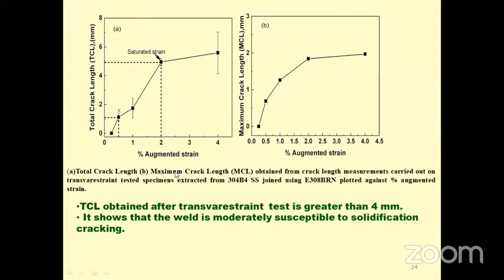So when we tested this material, we also saw that because the total crack length is above 4 mm, it is moderately susceptible to cracking. Whenever we want to use this electrode for an application where the restraint is lower, that is, the geometrical restraint or the thickness of the base metal to be welded is smaller, we can go for this electrode because the restraint expected in those components will be low. So this will serve the purpose. In that way, it is moderately susceptible to cracking.